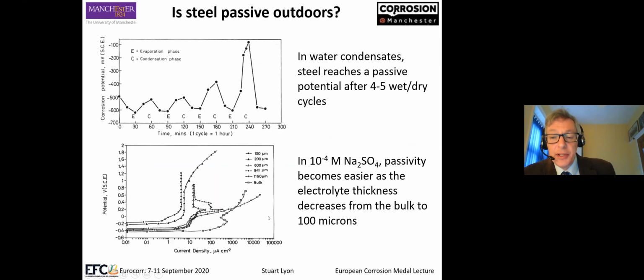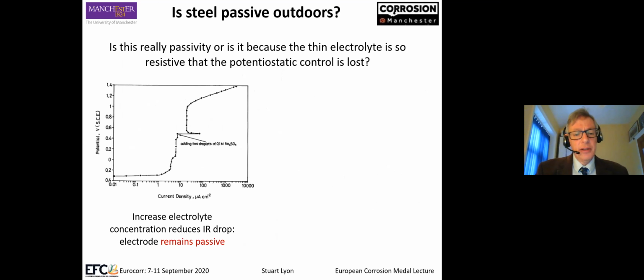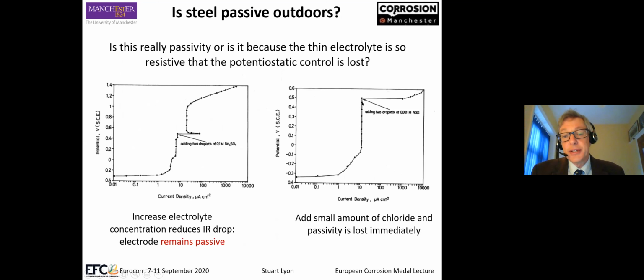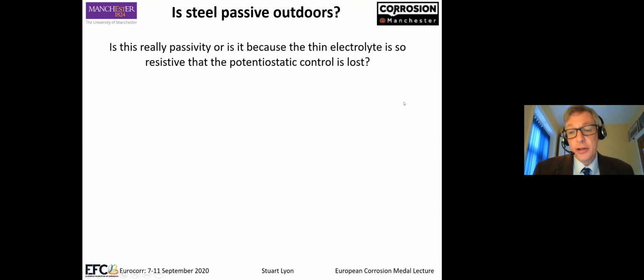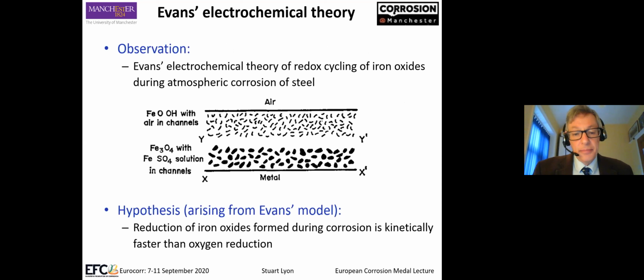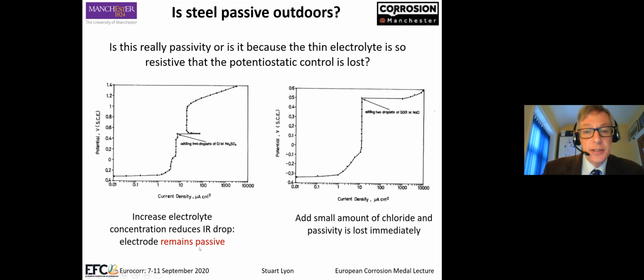If we do electrochemical experiments in really dilute electrolytes, this is 10 to the minus 1 millimolar sodium sulfate, then the passivity becomes easier as the electrolyte thickness decreases from the bulk to 100 microns. A question that came up with the review of the paper was, is this all IR drop in the electrolyte? So we check that by increasing the electrolyte concentration by adding 2 drops of 0.1 molar concentrated sodium sulfate. Passivity stays the same, IR drop is reduced, and we retain passivity. However, if we add chloride, it immediately starts pitting and we get a big increase in current. So the material is indeed passive under these conditions.